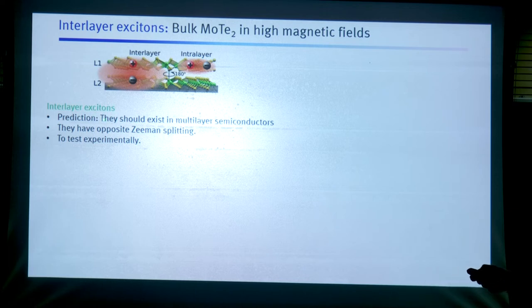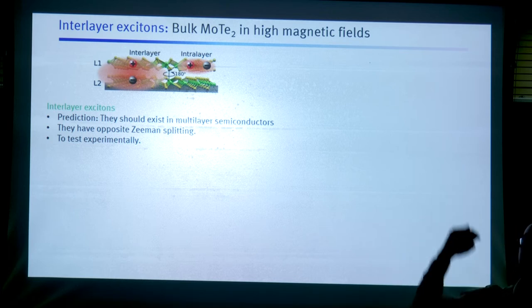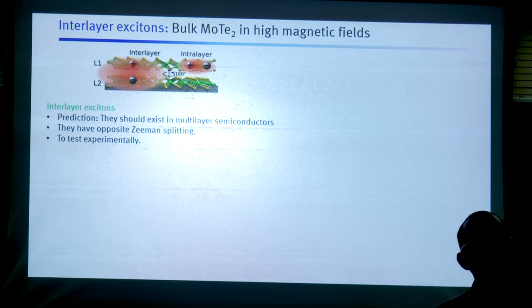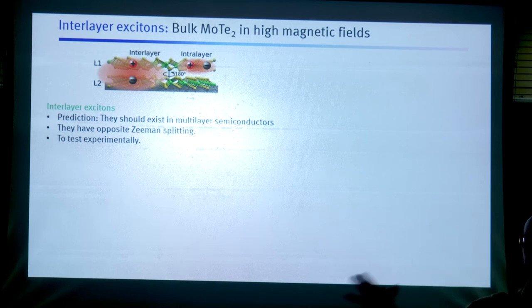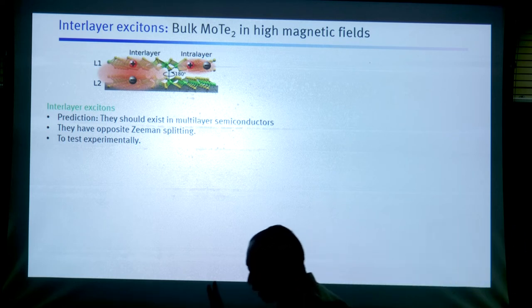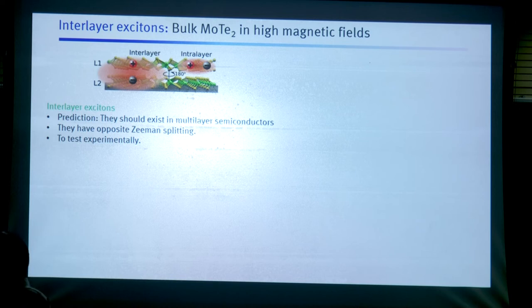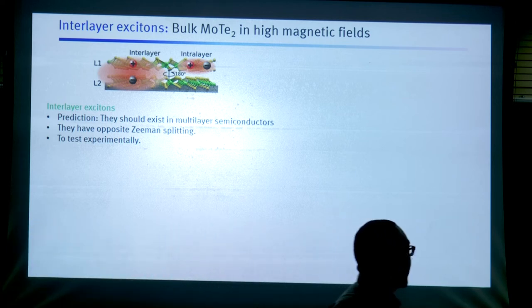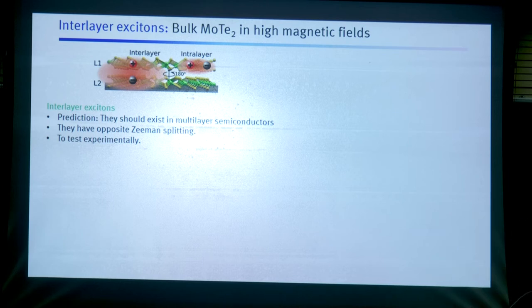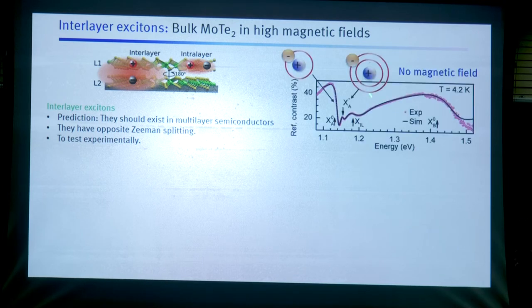Now, this was our prediction that they should exist in multilayer structures. The point is that for these two excitons, if one does a back-of-the-envelope band structure, we know that their Zeeman splitting should just be opposite. So that is one signature of intralayer and interlayer excitons. If you have two peaks lying close by, which have opposite Zeeman splitting, that could be one signature that there are interlayer excitons. So we have to apply a magnetic field and check Zeeman splittings. Let's take a look at this spectrum.